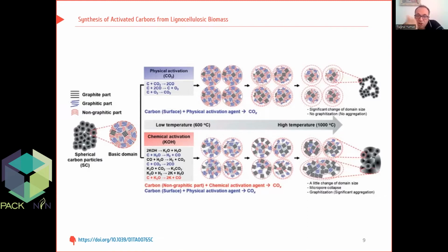The physical activation process occurs non-selectively on the carbon surface and gradually reduces the basic domain size, while the chemical activation process occurs primarily in non-graphitic parts within the material. However, water and carbon dioxide molecules are generated during the chemical activation, and so chemical activation can also reduce the basic domain size because physical activation occurs at the same time.